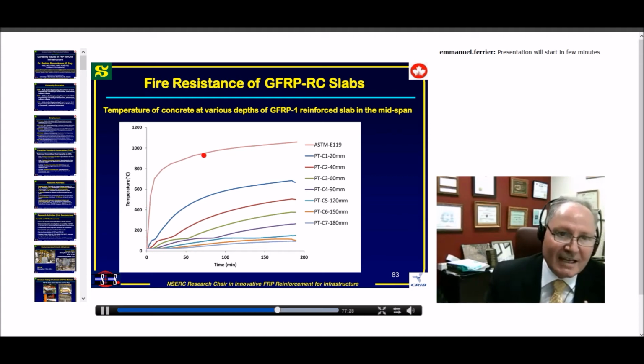And then increasing and going to almost 1,100. This is where we reached the curve. And this is all the thermocouple temperature, and this depends on the concrete cover. We have the slab. It has, I think, 230 millimeter thickness, and the first one is 180 millimeter from the bottom. And as you can see, it's the lower temperature. Even at the maximum, it reached less than 170 Celsius, as you can see, which is well below